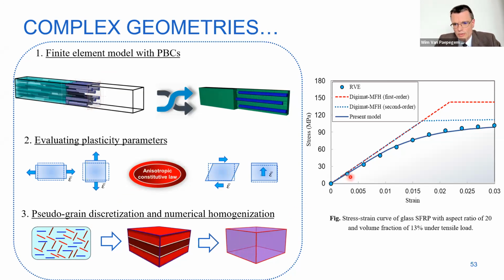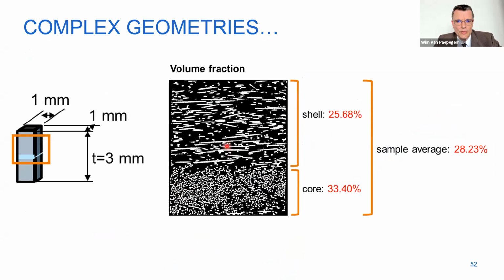So here you see that this can work. This is the stress strain curve. The circles are the finite element simulation of this RVE. And then the fitted line, because in this case it's still a fitted line, is the anisotropic plasticity model. And that we then use with different orientations and built in the orientation tensor from these sides.